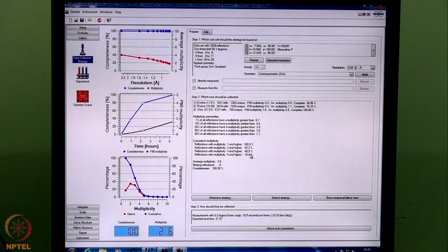So if we put those two pieces of information, then what it gives is the total amount of time that is going to be needed for this particular data collection. So overall data collection time is 52 minutes for the first run, 78 minutes for the second run, and 3 hours for the third run. So altogether the data collection will take about 5 hours.